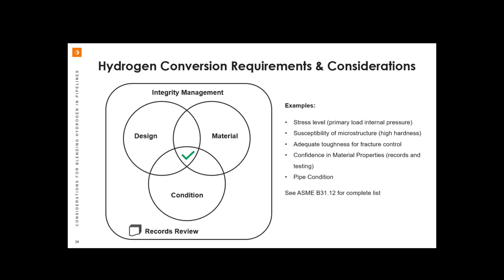So we note that at high stress levels, we can have issues with stress-oriented hydrogen-induced cracking. And so we need to pay close attention to the layout and supporting structure, as well as differential settlement in our facilities. For the material, we need to perform adequate historical material testing, or have sufficient records to prove out our material. We want to have enough confidence in our material properties and the base metal, heat affected zones, girth welds, and we really want to pay close attention to the condition of the line. We've just seen how imperfections can be negatively impacted by the introduction of hydrogen.